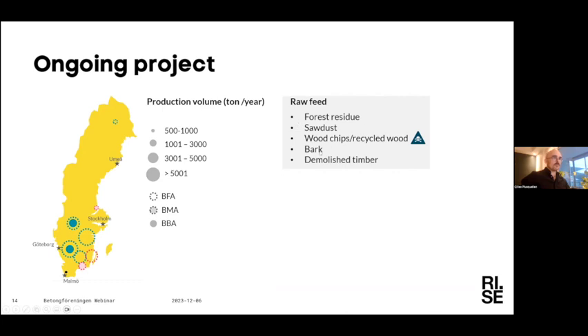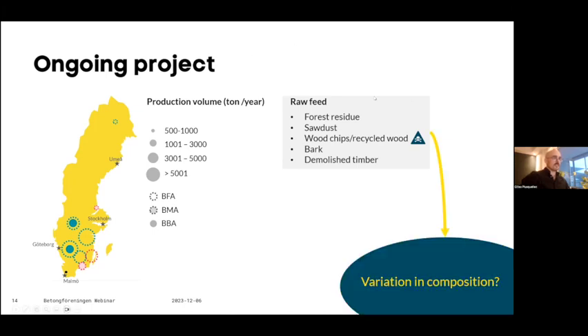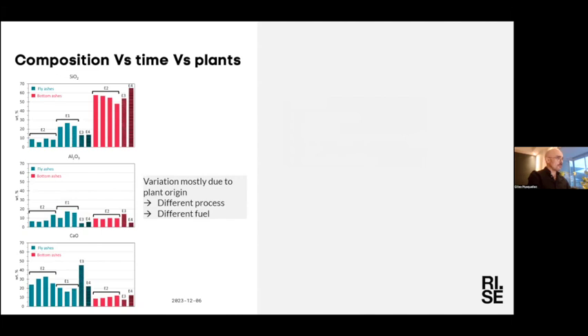Depending on what was used to make those ashes, we made a pre-screening. Everything that comes from recycled wood, we put aside, because then there was a risk of paint containing heavy metals that you don't want to have. But still, because of all this variety, we were a bit afraid of the variation in composition of all those ashes. So we made constant analysis of all the samples that we get.